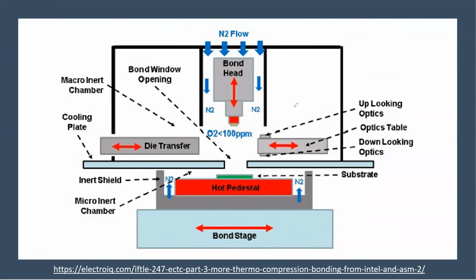And everything had to be inert gas, right? You don't want to oxidize your copper. And there's oxygen control at less than 100 ppm. And your die transfer, everything had to be kind of floating, right? In a way that you could adjust everything. And then you have to adjust your substrate temperature, your hot pedestal.